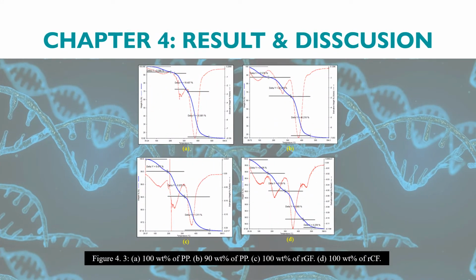As a result, from the testing, figure 4.3 shows 4 graphs. First, 100% PP, second, 90% PP, third, 100% recycled glass fiber, fourth, 100% recycled carbon fiber. The result suggested that the degradation curve had shifted from its original position. This means the increase of recycled carbon fiber affected the thermal degradation behavior.